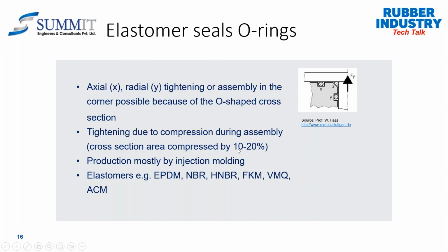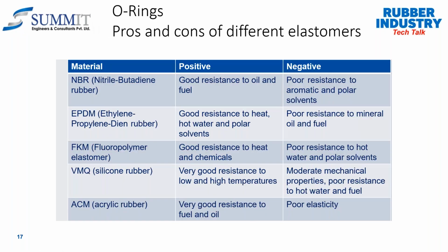The most important parameter: the elastomer. Now I would like to go to the application point of view. The oil seals or the O-rings. The O-rings are very important. Normally they are made of EPDM, NBR, or FKM. Many such different materials are manufactured with the injection molding or the compression molding process, and usually 10 to 20% of the cross section is compressed for the application when you insert it. Now you can imagine the forces required for that will be enormous, and that is going to create a difficulty for you in the application part of it.